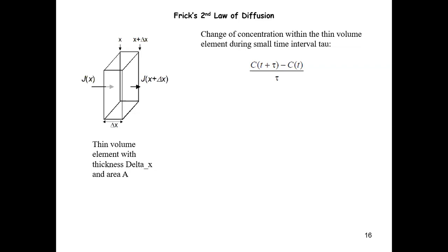So this equation is even less dependent on the material system or on what state you're looking at, right? It doesn't really matter whether it's a liquid state or solid state. It's based on the continuity equation, or sometimes called the local conservation equation. So now we're going to quickly show how we get this. Suppose we still have that trunk of solid material, but we only look at a very thin slab of that material. I didn't show anything within this, just imagine that you have some material in between, right? Now what I'm interested in is the rate of change of concentration within this very local volume per unit time due to flux, right?